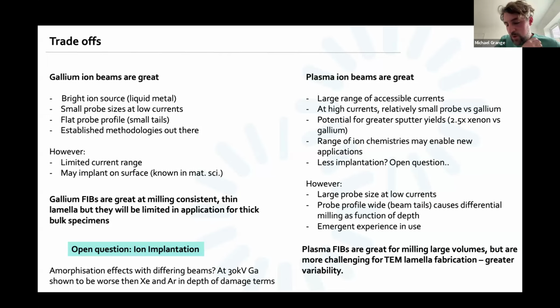And one really important aspect to consider, and one of the real reasons why plasma ion beams were generated in the first place, is the fact that you can have implantation onto the surface of the sample. So if you have an aluminium sample, for example, and you use a gallium ion beam, you can get alloys. How that affects biological specimens is really difficult to determine, especially under cryogenic temperatures. Maybe EELS would be able to tell us, but that requires very high electron doses.